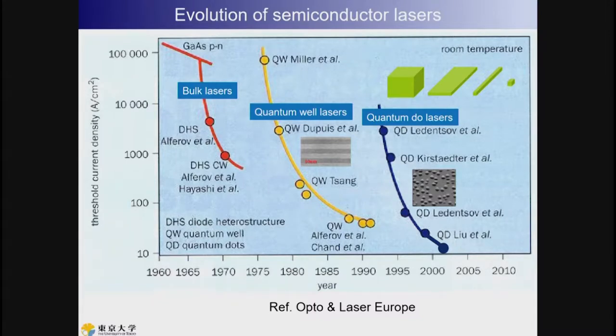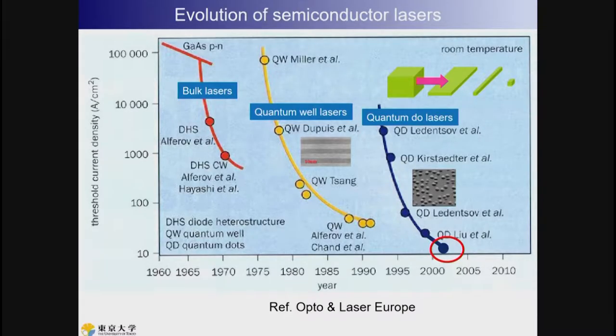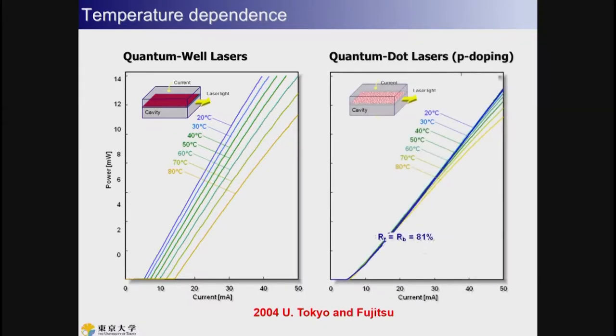Indeed, this is the evolution of the semiconductor laser with respect to the threshold current densities: bulk lasers, quantum well lasers, and quantum dot lasers. Nowadays, the lowest threshold current density is achieved by the quantum dot lasers. The evolution came from the bulk laser to quantum well lasers, quantum wire laser was skipped, and finally we have come to the stage of using quantum dot lasers for practical applications. Indeed, in 2004, I demonstrated the temperature stability of the threshold current using quantum dot structures in the active layer in collaboration with Fujitsu Laboratories.